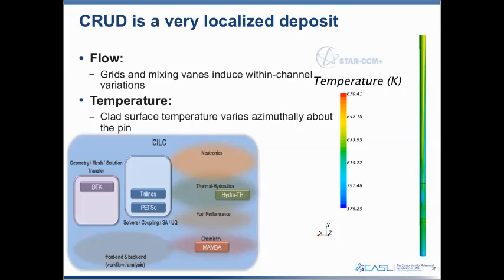So what you see here on the right is just a single rod with a grid spacer, located about 15–20% of the way up from the bottom, and the flow is going up. The variations you see when modeling this with CFD are flow variations that lead to temperature variations on the clad surface. That variation is really azimuthally changing around the pin.